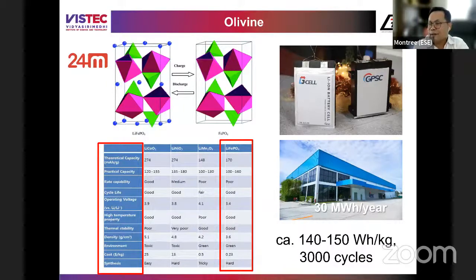That's why when we normalize by the battery, it is like the load, right? If we look at EV, we carry the battery, that means we carry the load. We need to have energy for the battery weight as well. So we need to reduce the weight of the battery. So LFP is not good for long range vehicles because it's too heavy, but we get the benefit in cycle life because it does not release oxygen gas easily. We have at least 3000 cycles and can have fast charging. That's the good thing about LFP. So it's suitable for ESS, energy storage, right? Stationary energy storage or short range, e-bike, scooter, e-motorbike.